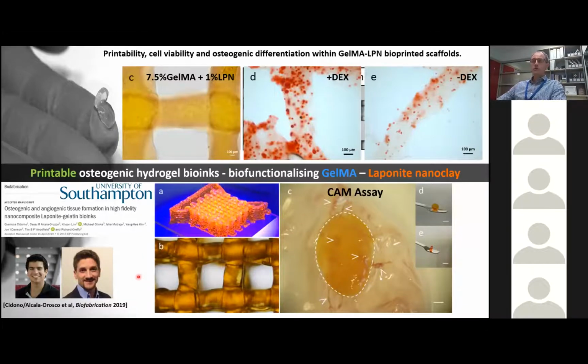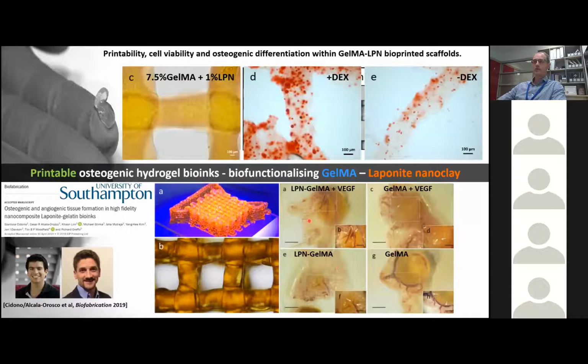What we also wanted to do, though, was try and demonstrate in an ex vivo model. So this is a chorioallantoic membrane assay, so a chick egg assay, where we're trying to look at then the sequestering of VEGF and vascular network formation within this particular model using the GelMA-Laponite constructs. So just very briefly, again, if we could take our GelMA-Laponite in the presence of VEGF, we could see that we could get vascular invasion, or at least vessel formation within these constructs.